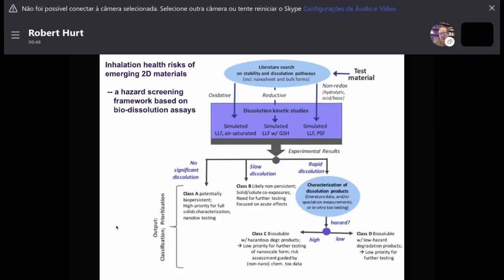And based on that, one can do simple tests, dissolution kinetic studies, in a simulant that is picked to match the dissolution pathway that you would predict. If it's oxidative, you do work on air-saturated solutions. If it's reductive, you'd add an antioxidant like glutathione.